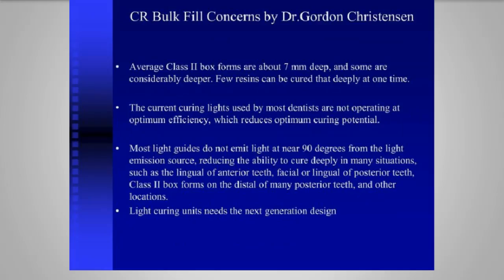So Dr. Christensen is really keying in on the light carrying capability and consistency of the photons, and also the volumetric depth of the box. According to Dr. Christensen, a class 2 box can go even down to 7 millimeters deep, and if you're curing to 5 millimeters, something's not getting cured. So we have to find a way for something to dual cure down there and or get the light down in a deep shaft.